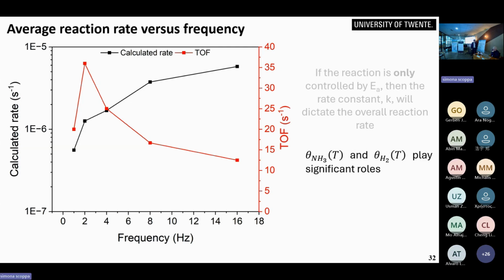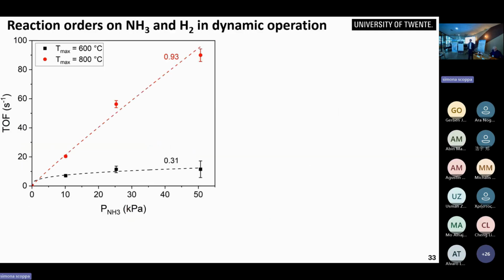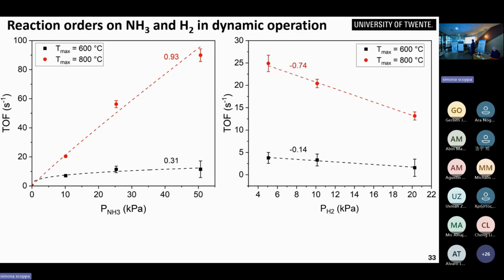Now, what this means is that there might be something else playing against us during this process. And what you see is that there is an optimal frequency at which this process is enhanced to the maximum. That's when you reach this very high turnover frequency of 35 seconds to the -1. And for that, we actually had to do quite a few kinetic experiments. But generally speaking, if you look at the apparent reaction order on ammonia, the lower the temperature of the maxima that we apply, the lower the order. So that would suggest saturation kinetics, which makes sense. Lower temperature, things stick longer on the surface. Higher temperature, things do not stick so well.